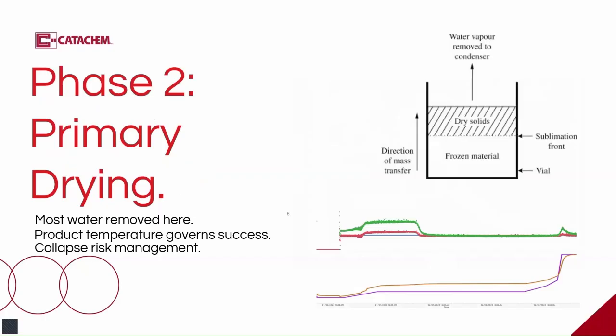Primary drying is where most water is removed, and it is also where most failures occur. In primary drying, ice sublimates under vacuum. The shelf provides heat. The chamber pressure and the condenser pull vapor away. The product temperature must stay below the collapse temperature for amorphous systems or below the eutectic melting point for crystalline systems. These terms will be explained in more detail on the next slide.